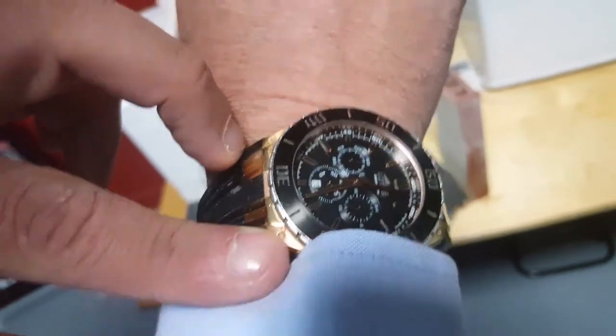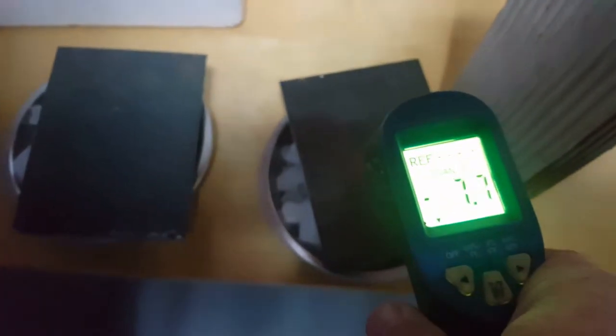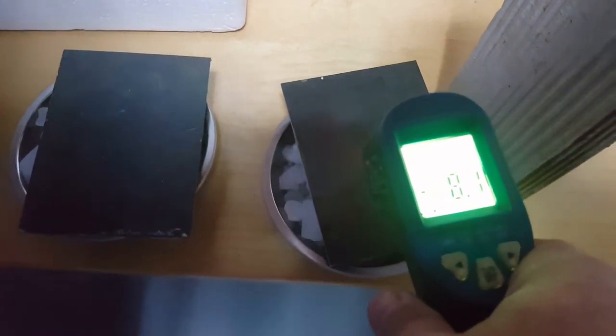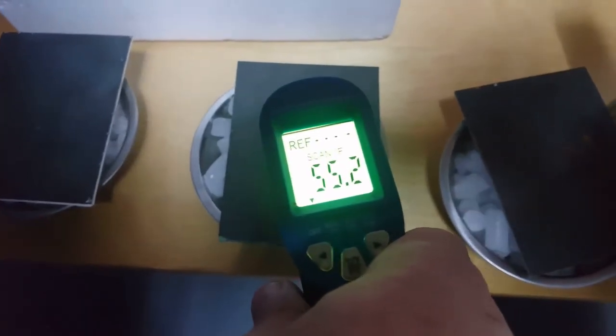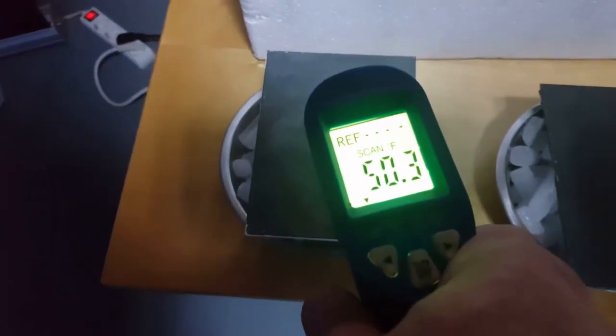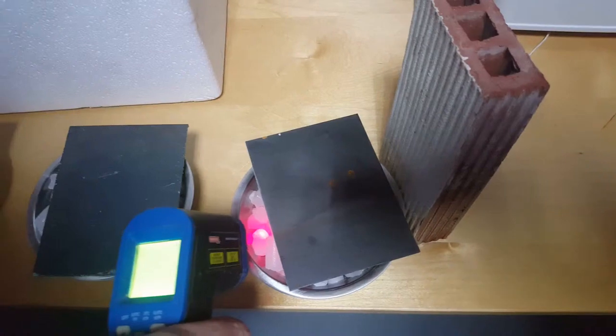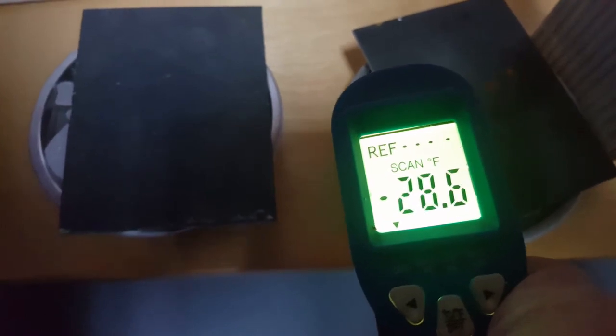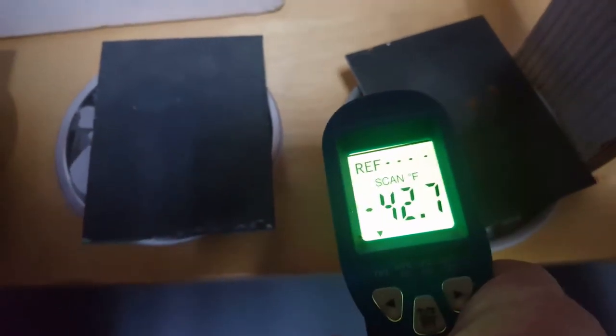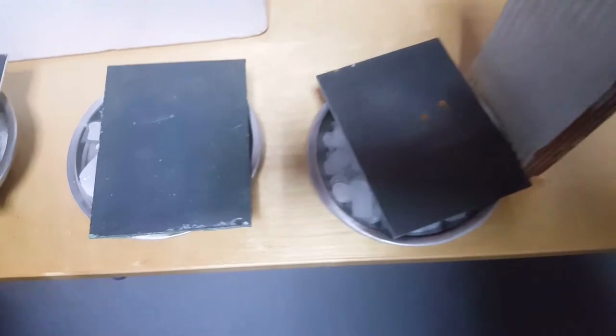So it's been a couple of minutes since we first started. We'll take another reading. The uncoated sample is already at -7, -8 degrees Fahrenheit. Our cork sample is still at 55 degrees Fahrenheit, and then the ceramic is at 50 degrees. So right now we're seeing temperature differences between 55 degrees and 60 degrees Fahrenheit. For reference, the temperature of the dry ice is still around -40 degrees Fahrenheit.